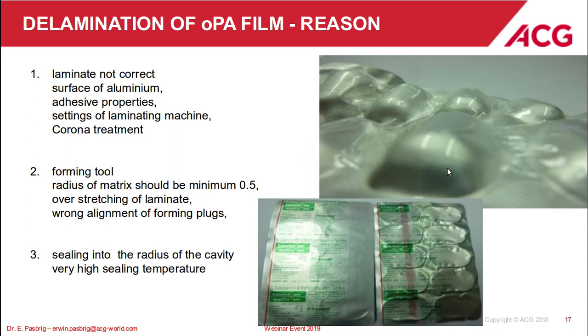OPA intends to shrink because it's a biaxially oriented film, and then one further. If it's sealed into the radius of the cavity, so the material during the forming process is not adjusted from time to time, you get a moon effect on it as well. Even with primer you can have it, because the OPA gets punctured, and so there are holes. The humidity immediately will go into the material and affect the adhesive.